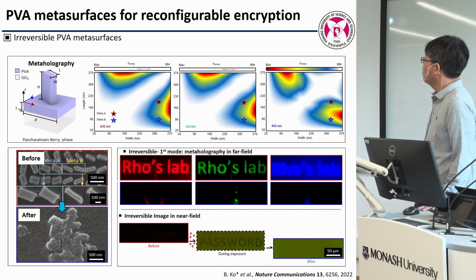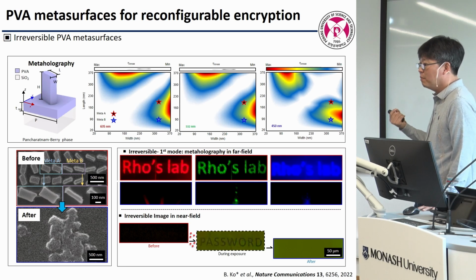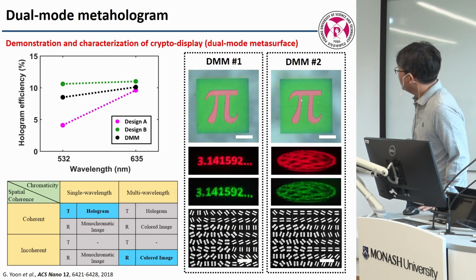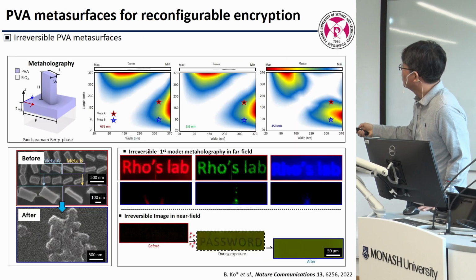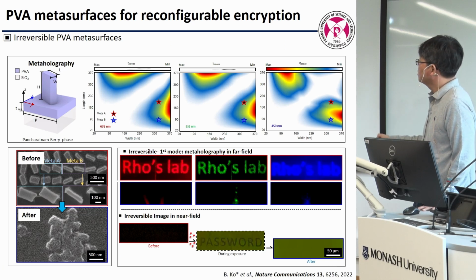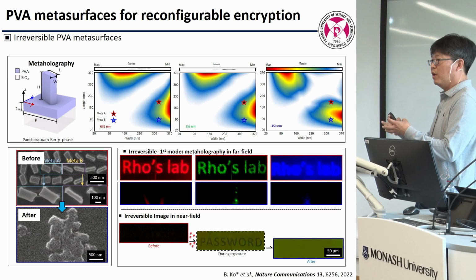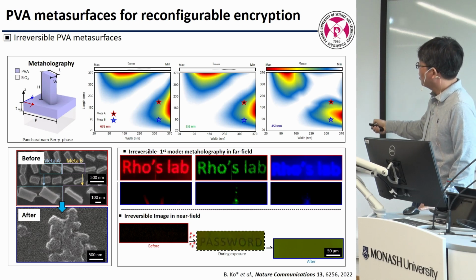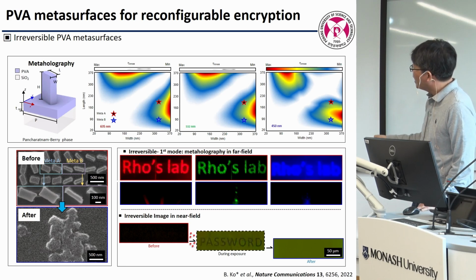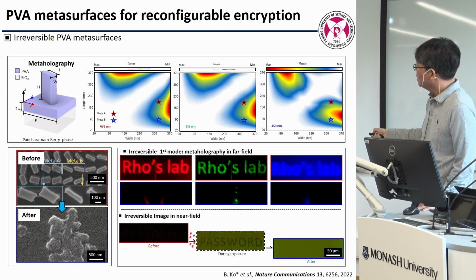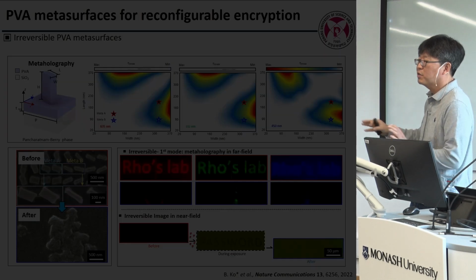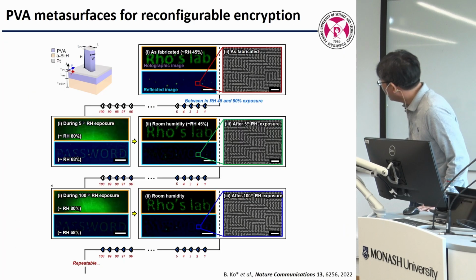And further, this is applied to some engineering applications, humidity sensing and image encryption. So we changed the silicon to a polymer called PVA hydrogel. And the hydrogel absorbs water and becomes fatter. And while the humidity comes in, they get fatter and stick together, so it's like screwed up. In the beginning, they have a hologram image because their shape is correct, but when humidity comes in, their shape becomes ugly, and there is no more hologram. So it's structurally broken.